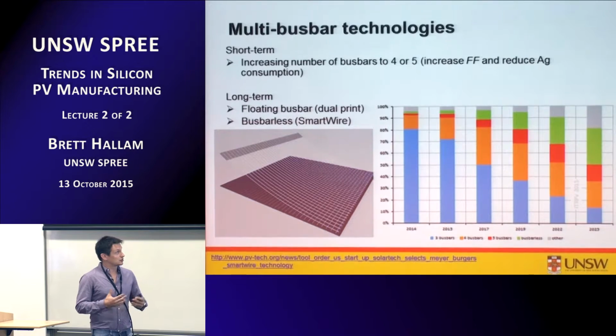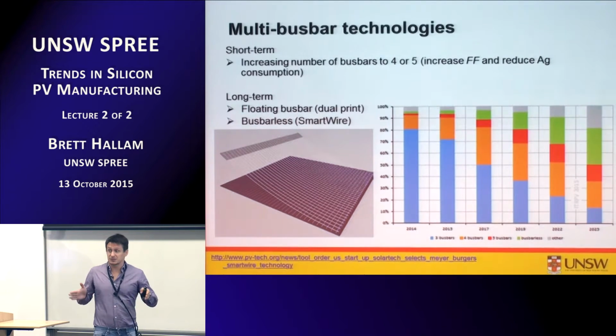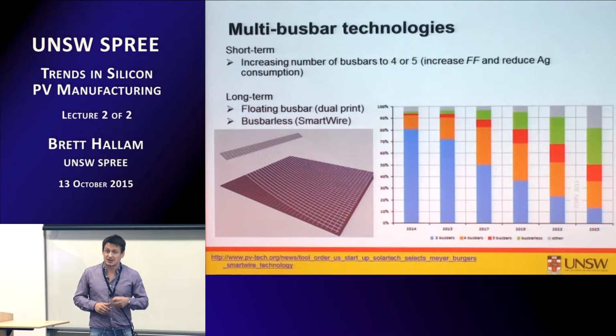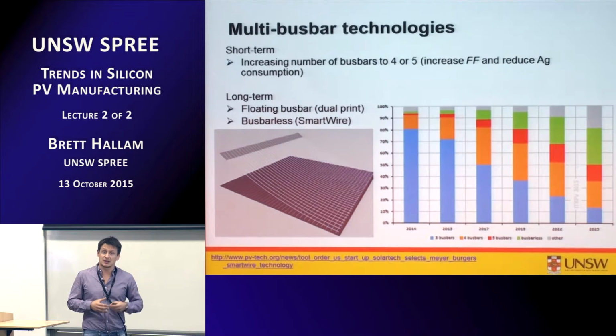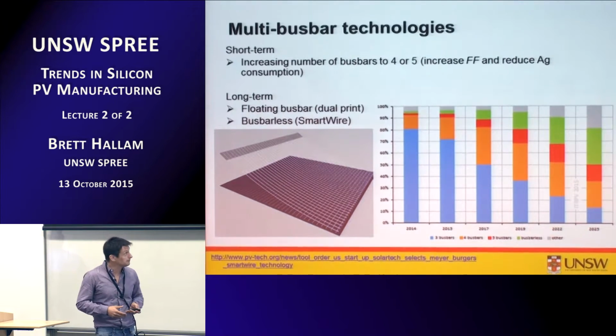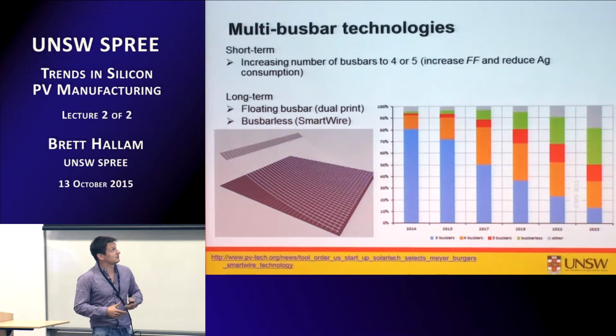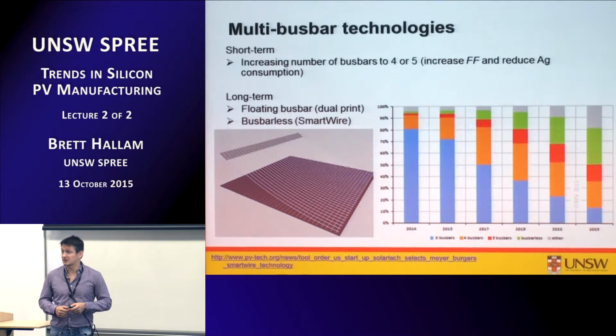Another trend that's certainly becoming apparent is increasing the number of bus bars on the solar cell. As we increase the number of bus bars, we can potentially make the bus bars narrower and reduce their silver consumption, etc. It also relaxes some of the constraints on how far the fingers have to conduct the carriers to get to the bus bar. So we get increased fill factors and reduced silver consumption. The trend of the industry is certainly going towards 4 bus bars, potentially 5, but most of it looks like it's going to 4 bus bars.